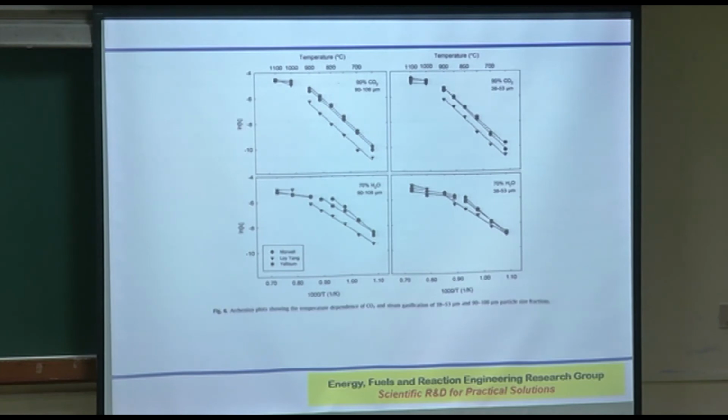And for these particle sizes, the determination is completely done: either this small one or that large one, they are in the chemical reaction control zone for this type of chars, because they are so porous that for both it is giving the same chemical reaction controlling rate